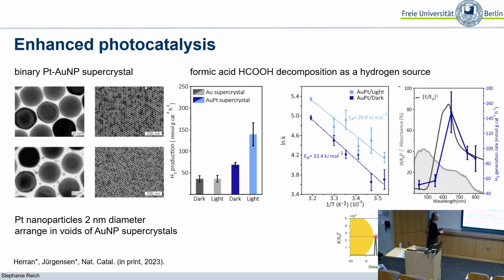And I mean, if you've heard about plasmon-enhanced chemistry and catalysis and so on, people always discuss whether there are hot electrons that are created and extracted from the material. I just want to stress that we do not think that this is a mechanism in our system. It is simply the fact that you concentrate the electric fields very much. So here's a simulation where you can see the concentrated field at the places of the platinum nanoparticles. So you do a catalytic reaction with a much higher field strength, as if you would crank up a laser in the experiment, but it was done with a light source that mimics solar light.